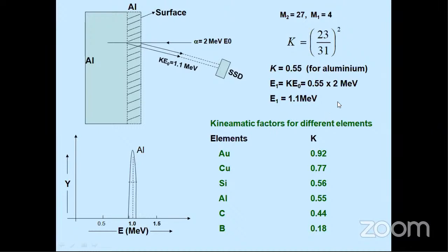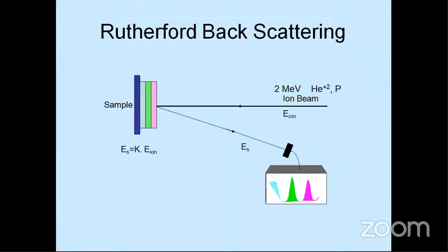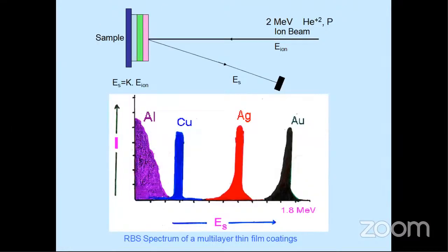So you can differentiate. So for example, this is a 2 MeV particle. So this is our sample, say, for example. It has got copper, gold, aluminium. So if you bombard this sample with the ion beam, then the scattered beam will tell you which elements are present here. So gold peak will be different, silver will be different, copper will be different.